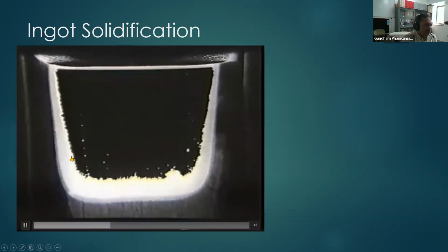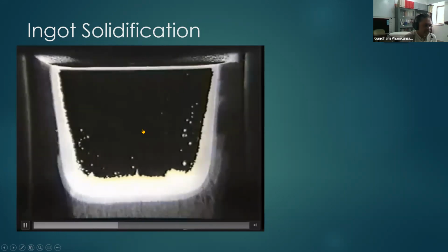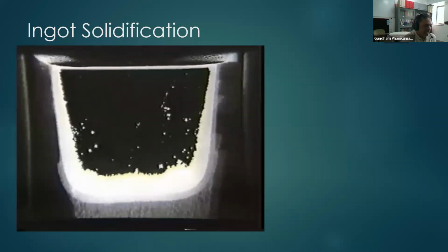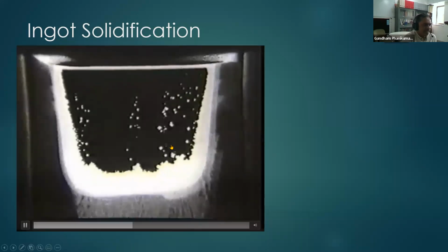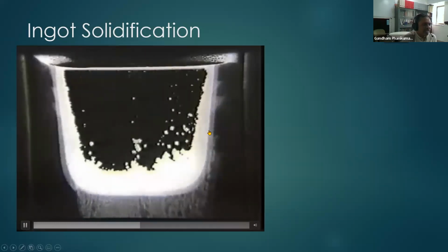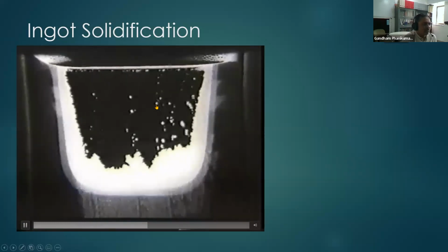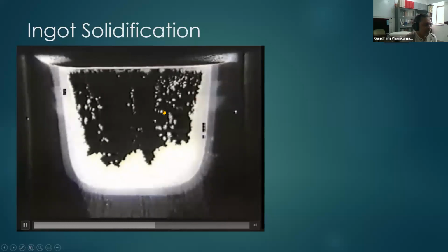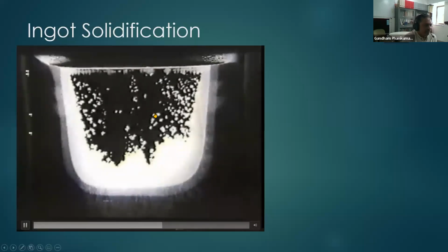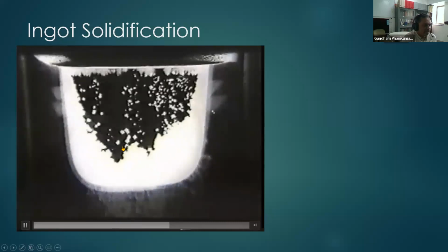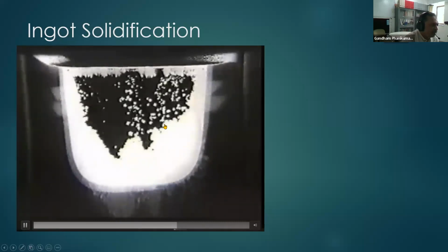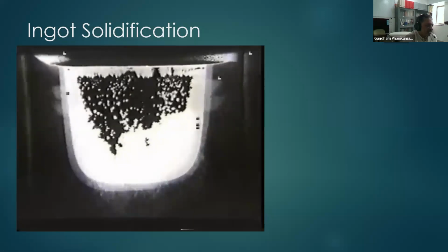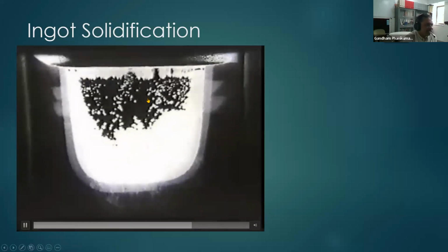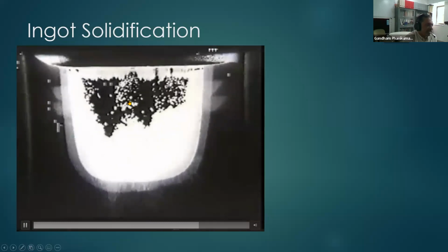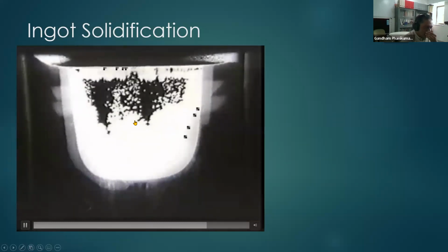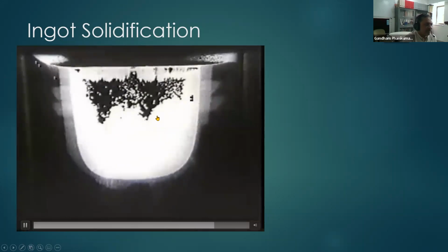So the contrast of a bright region being solid and dark region being liquid is because of refractive index difference. And you see that the solid that is forming is actually moving around. It's not growing straight from the side or bottom. It is actually moving around. So there's some convection that is also playing a role. And these solid fractions are getting accumulated on the bottom, which is how the equiaxed microstructures are seen, because each of these solid particles are growing in the liquid equally in all directions, and then they are getting deposited at the bottom, and therefore you see that the equiaxed zone can be explained.